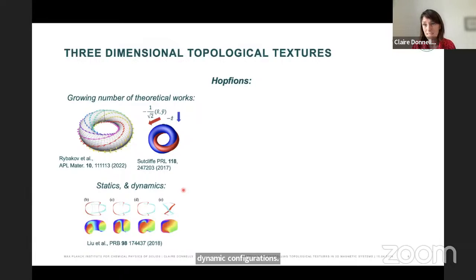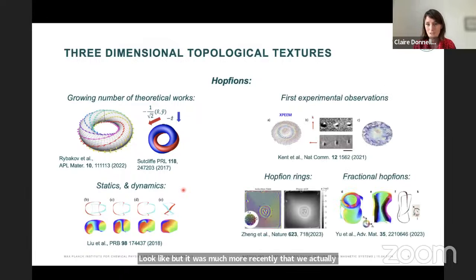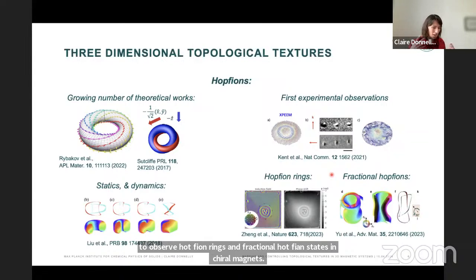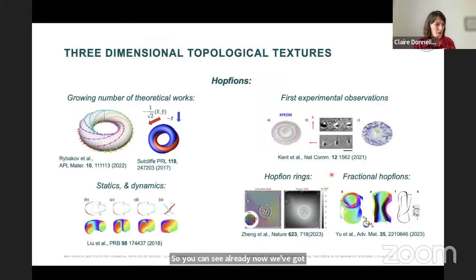But it was much more recently that we actually had the first experimental observations of such textures, both in these thin film heterostructures, as you see at the top, but also observed with electron microscopy. So albeit with two-dimensional imaging, they were able to observe Hopfion rings and fractional Hopfion states in chiral magnets. So you can see already now we've got a number of different possibilities and already first few observations of these complex 3D textures.